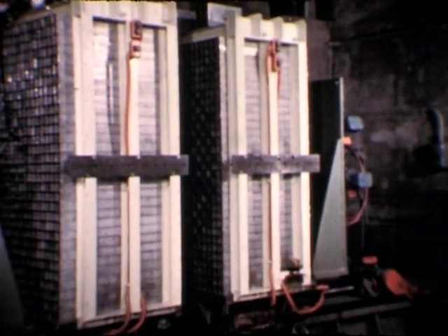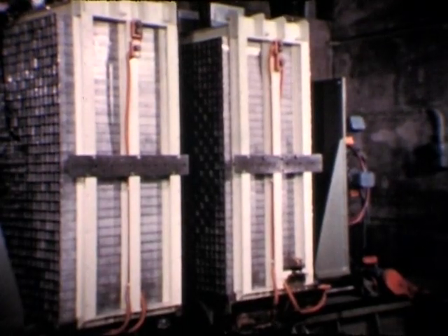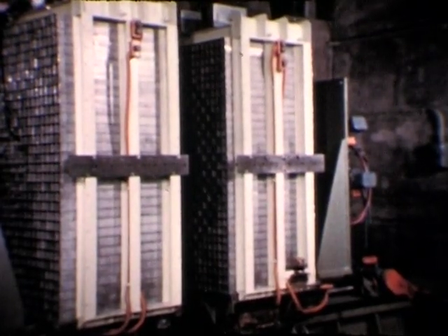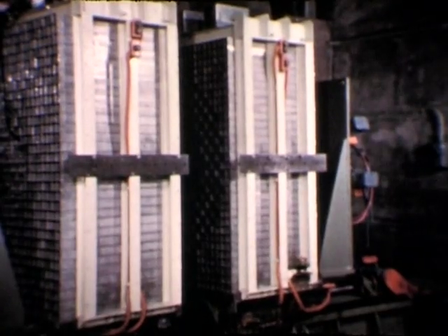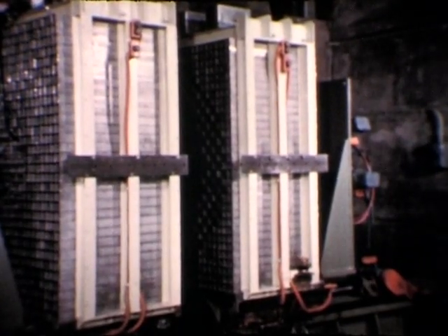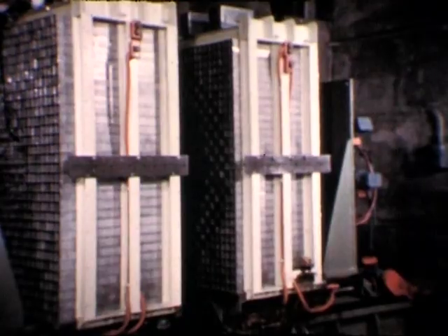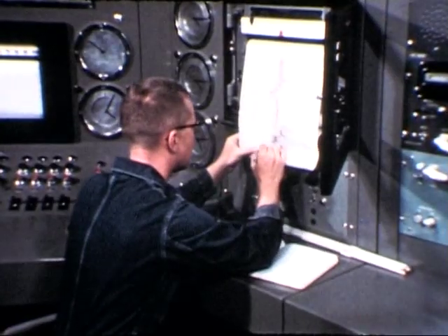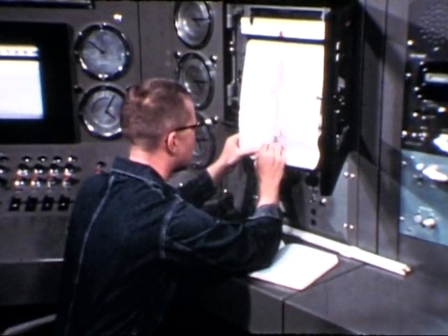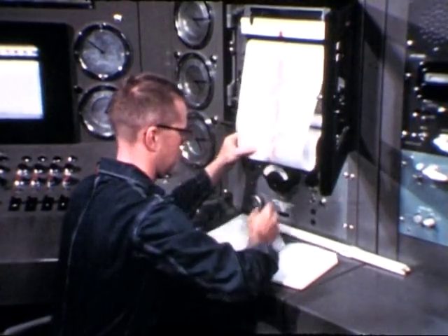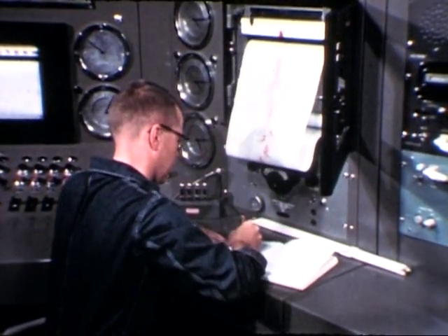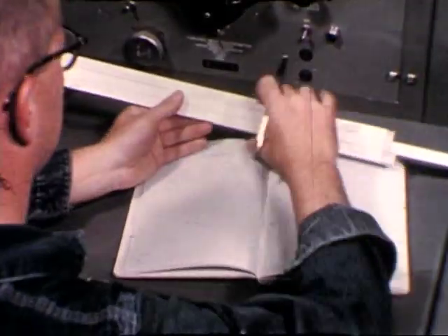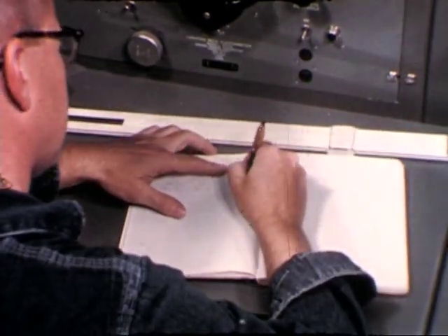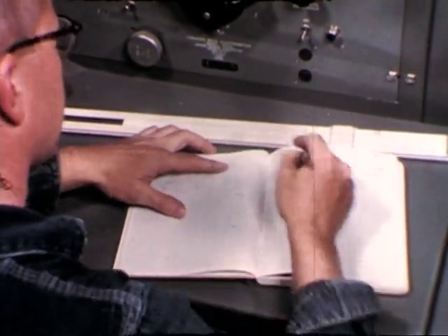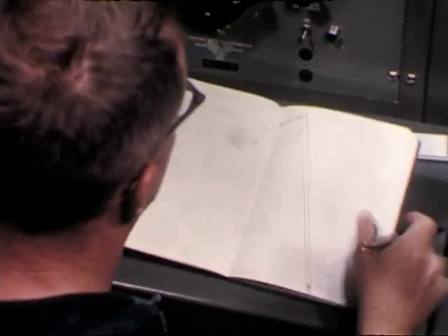Additional ZPR3 experimental information allows adjustments of the observed critical mass for slight changes in composition, burn-up, fission product poisons, type of control rod chosen, temperature effects, and sodium for aluminum equivalents. The completion of this portion of the Fast Reactor Program will define the nuclear characteristics of a uranium-235 core. Subsequent experimental programs will investigate plutonium fueling for EBR2.